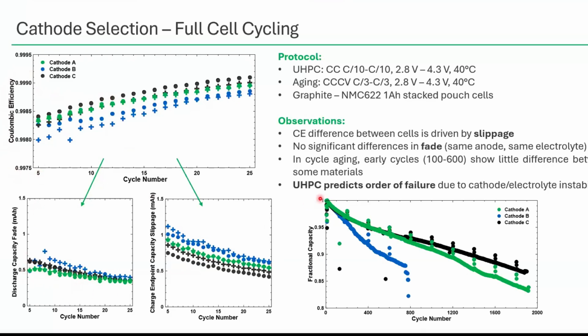We can see that when we go into looking at our long-term cycle aging out to a couple thousand cycles, right at the start, everything does actually fade very similarly. We see that in our just a couple weeks of UHPC cycling too. But really what ends up making these cells start to fail, to roll over, to maybe dry out of certain electrolyte components are these slippage-based reactions, not directly fade-based reactions that we see at the beginning of life. This black and green look very similar until about cycle 600 or so.